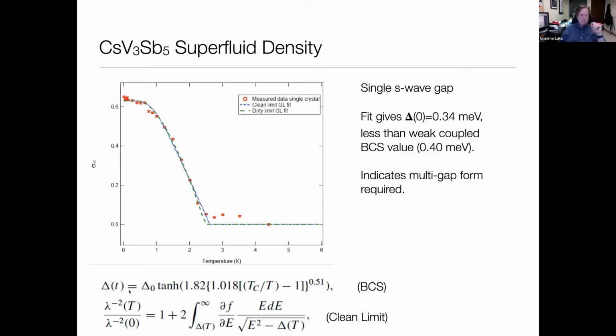We know in the clean limit, we can then calculate what the superfluid density is. It depends on basically states that have been excited over the gap. So here's the Fermi function, and we need basically the derivative of the Fermi function with respect to energy. We integrate this over all energies. This is basically part of the gap, looking like the gap equation in BCS theory, and from that we can actually determine, assuming for now a BCS form for the gap, what the gap would look like. And so here's the best fit that we get for that, shown in the blue here.